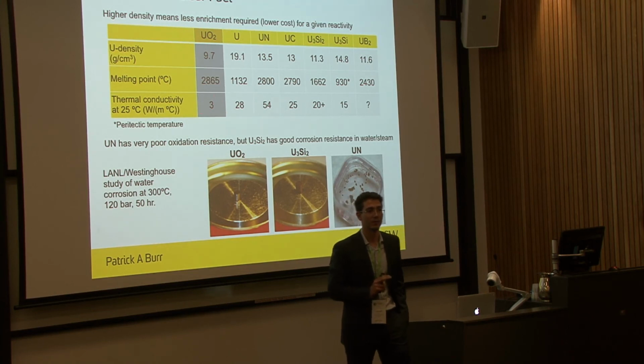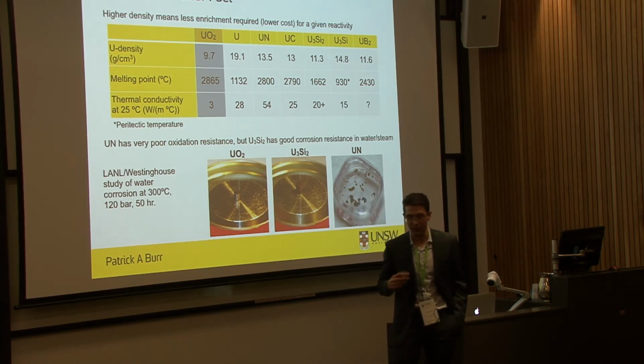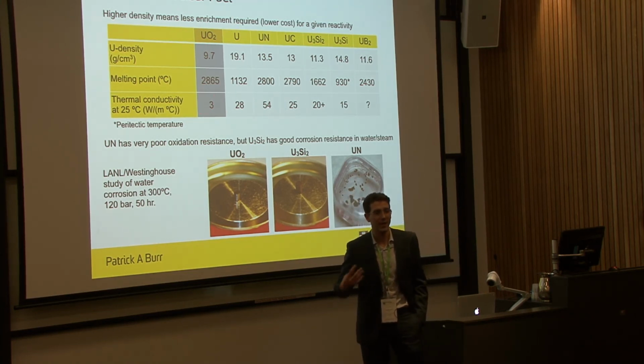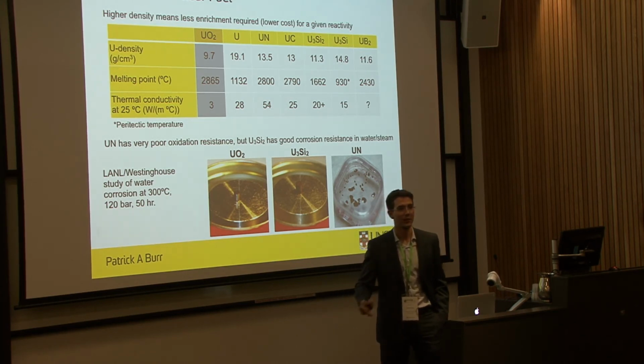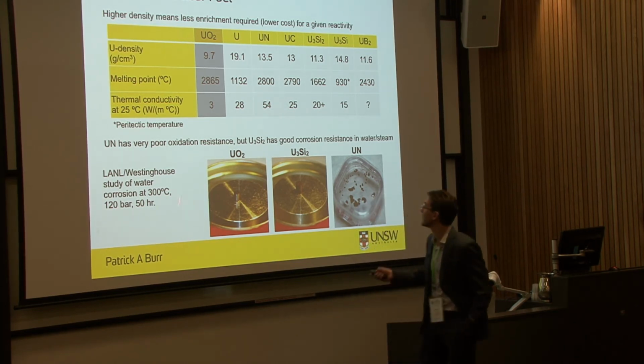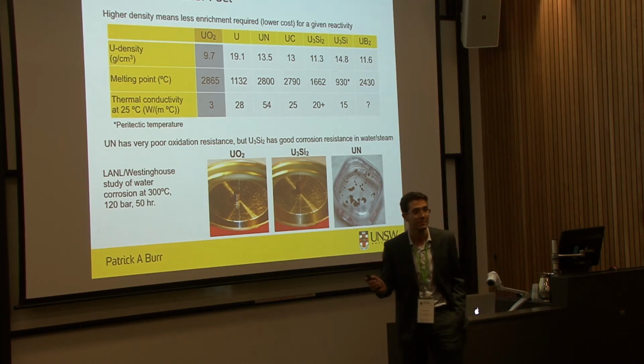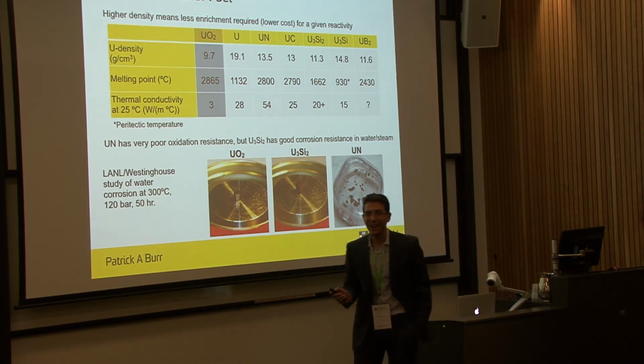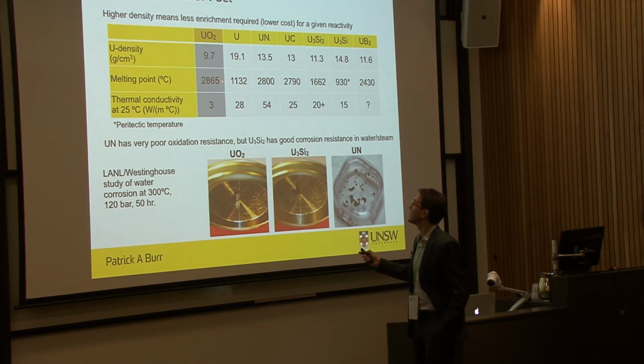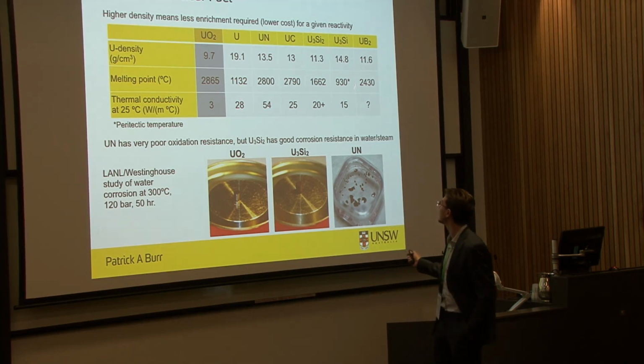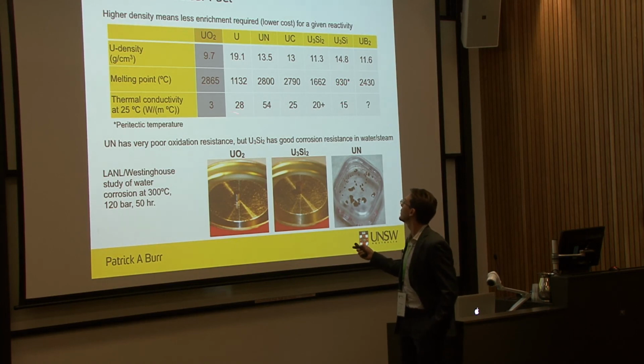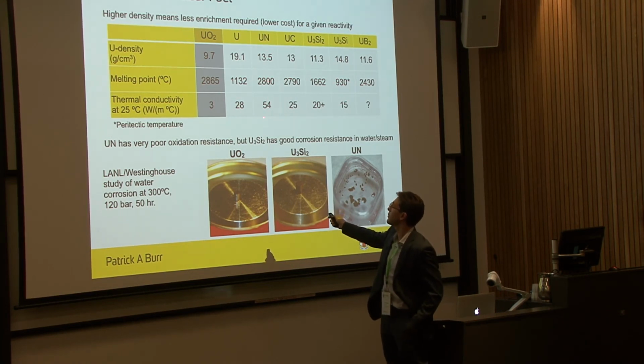There are two good aspects about that. First is that when you irradiate the material, the fact that the thermal conductivity degrades doesn't matter, because it's so poor to start with that it can't get any worse. The other good aspect is whatever material you come up with is going to be better. And that means that melting point matters less, because if you get such a good thermal conductivity as some of these materials have, then the melting point can be much lower. And particularly, you should notice uranium nitride, which has a very high melting temperature, incredible thermal conductivity,